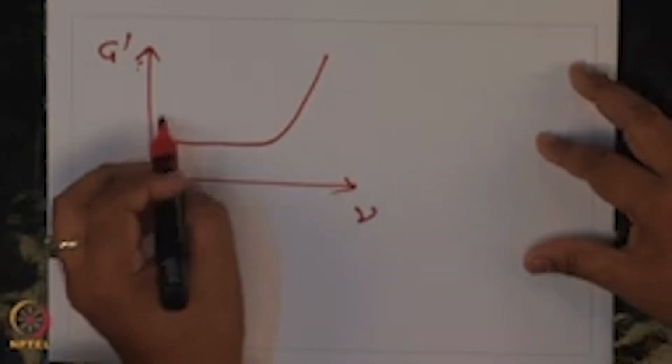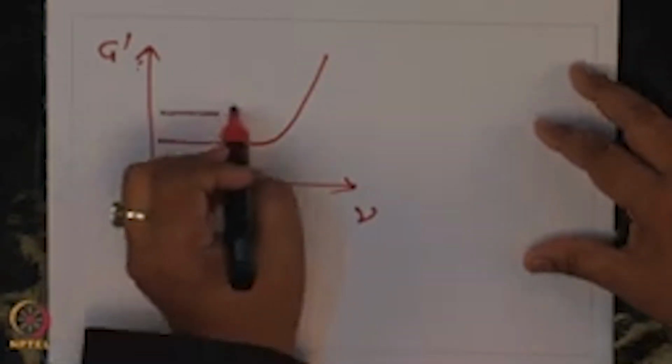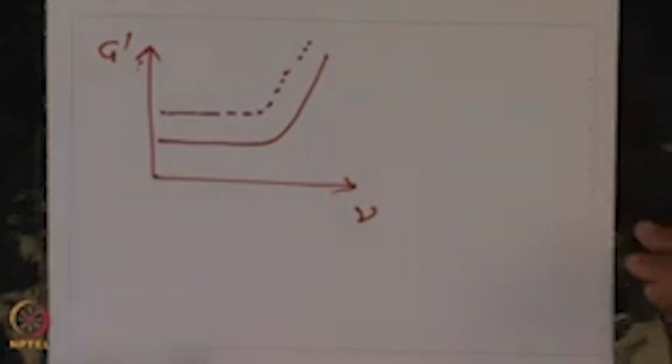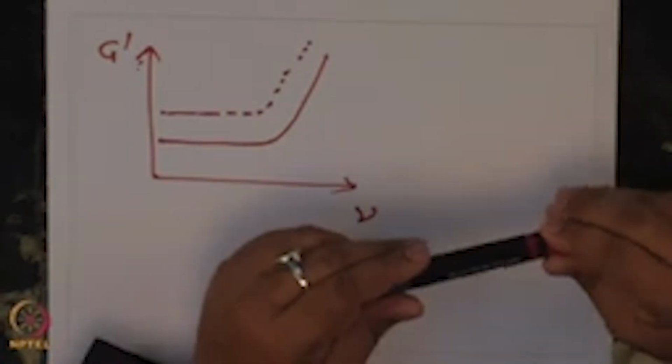Okay. And then if you were to do it at the higher concentration, this curve will just shift upwards. Okay. So, this is strain stiffening, and as we discussed in great detail, this kind of strain stiffening behavior is induced by alignment of the individual fibrils in the direction in which you are exerting the force.